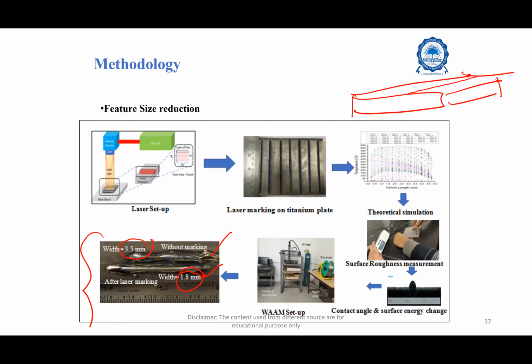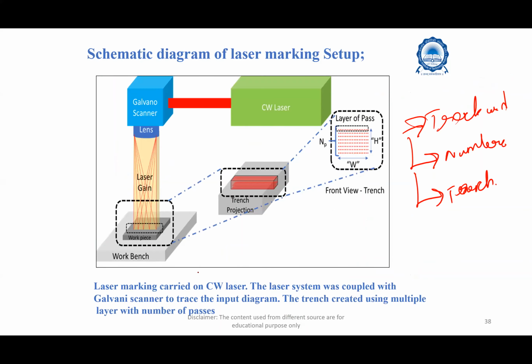For inducing the surface roughness, we are using a laser as a key player for creating the mark. For that, we have a 50-watt laser. This 50-watt laser is fitted with a galvano scanner, and it has a TEM mode of beam, which creates a shallower groove at the center. So TEM mode would be something like this.